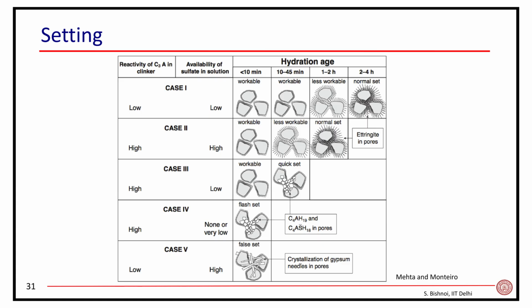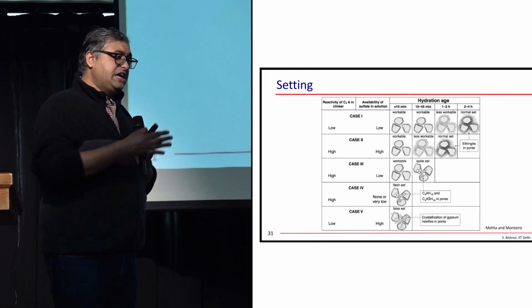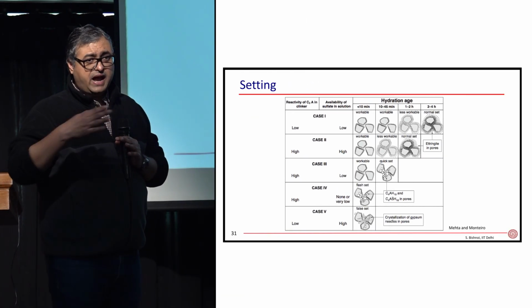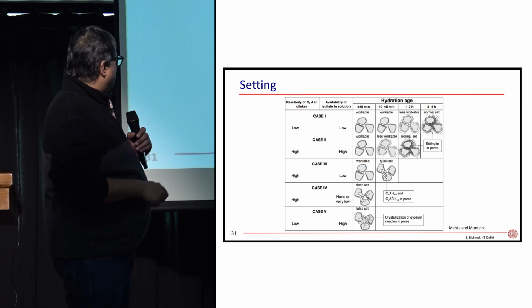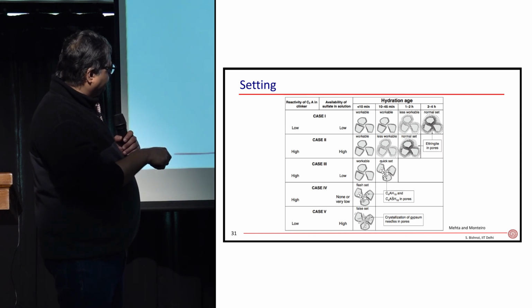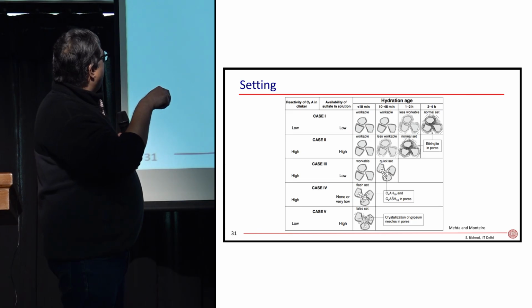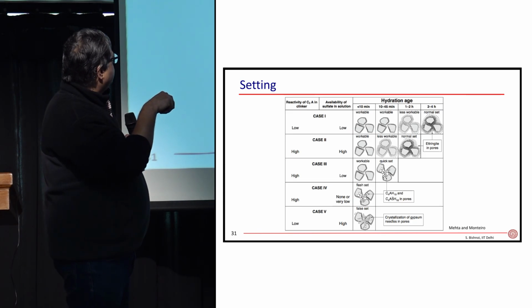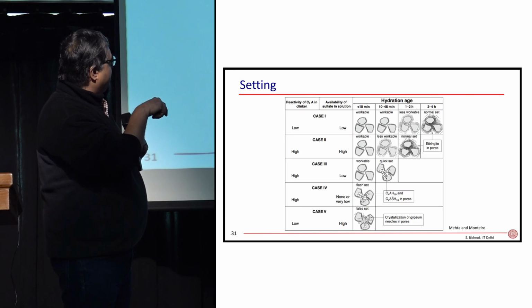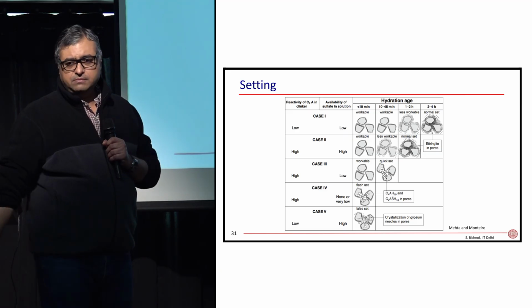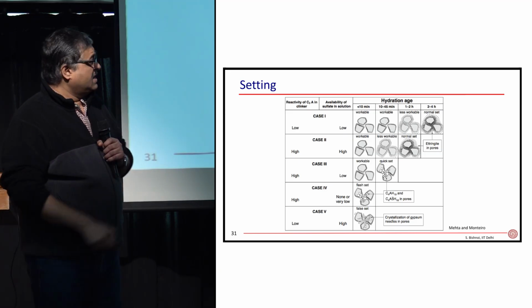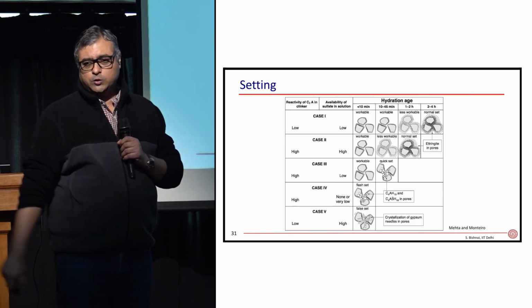These reactions are slower than the first reaction where hydrogarnet is produced, but the important thing is you have to have the right ratio between gypsum and alumina. If you have too little alumina, or too high an alumina and very little gypsum - if you don't put enough gypsum - the cement will still set quite quickly.